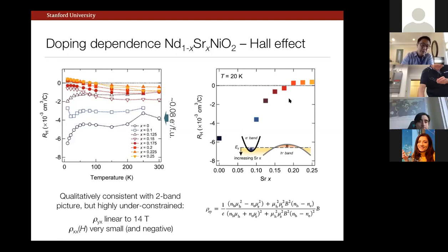Now we would love to be able to try to get some more estimated numbers out of this. Many of you in the audience are quite familiar, I'm sure, with this kind of 2-band fit. Our problem right now is that we are under-constrained, namely our Hall coefficient is linear up to, let's say, at least the 14 Tesla scale. The magnetoresistance is very small, and on top of that, it's negative. So it's not simply interpretable in a 2-band picture. So these are limitations before hopefully someday somebody can access the Fermi surface directly by ARPES or something. This is our current understanding.